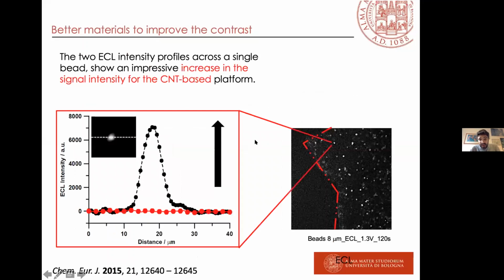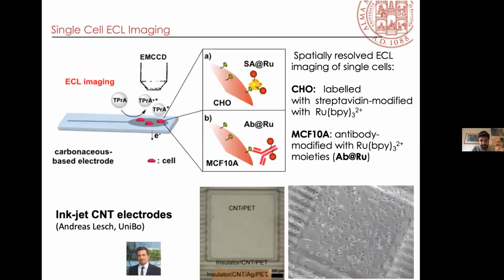Carbon nanotubes have a much higher emission compared with ITO, because the kinetics of TPA is faster, and so you can generate more radicals. These are single bead emissions. The red line is ITO, and the black curve is the emission from the carbon nanotubes film. That's very important, because if you want to work in the ECL field, you must optimize the working electrode material, because the emission that you can measure strongly depends on the electrode material.